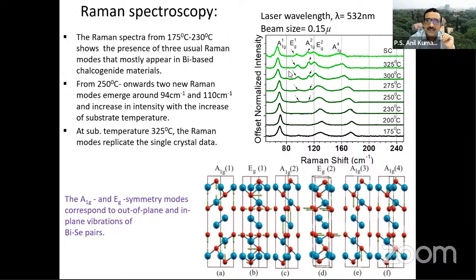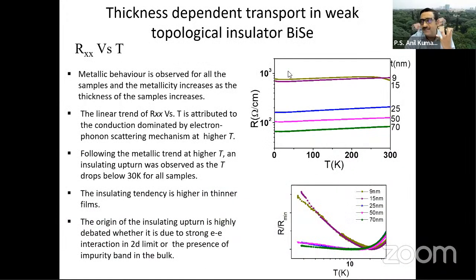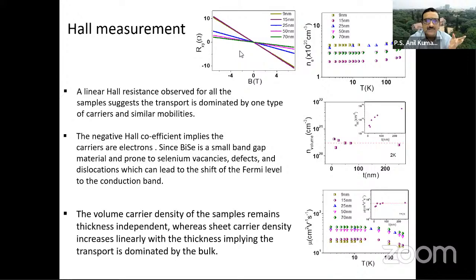That tells us that the quality of the BiSe film is acceptable. So now we have a choice of varying the thickness of these BiSe films and start looking at the transport properties. We have studied between 9 nanometers and 70 nanometers of BiSe film. We have also looked at the Hall data, and we see that the carrier concentration that we are getting in this BiSe is comparable to the carrier concentration that we were getting in the bulk material. But the mobility of the system has gone down.